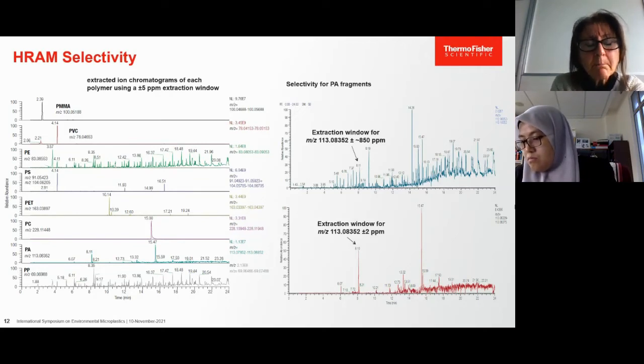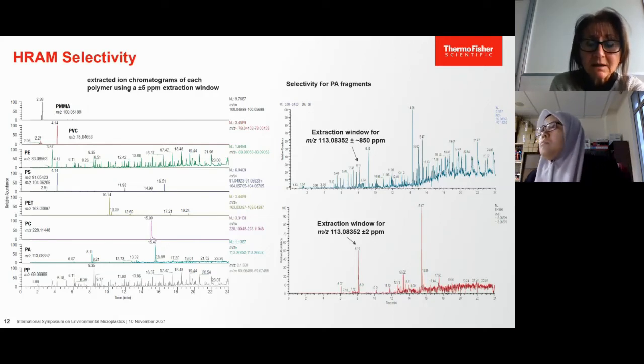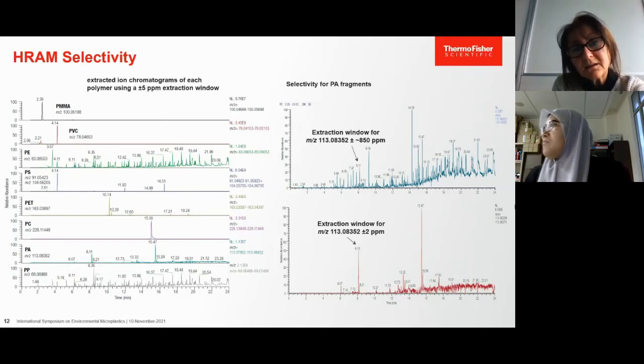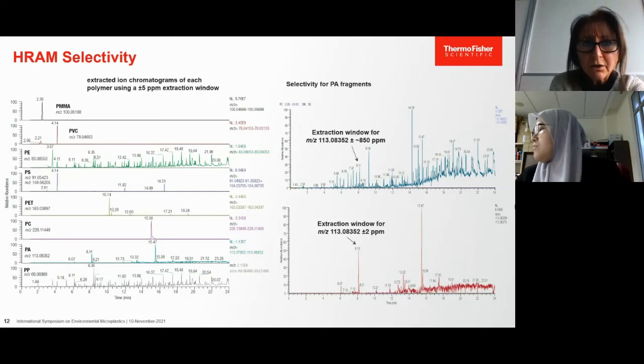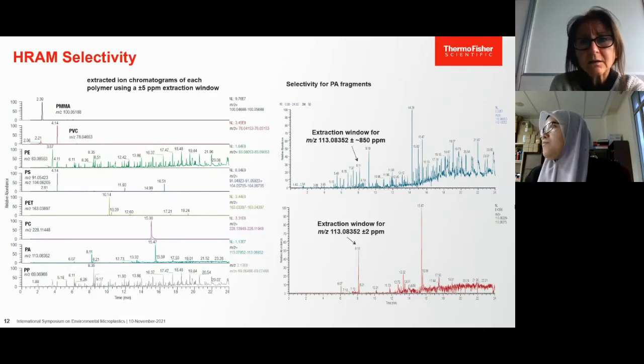In addition, the importance of high-resolution accurate mass detection in order to improve the selectivity is demonstrated on the right-hand side of this slide for the polyamide fragments, using a much wider extraction window in order to simulate a low-resolution mass spectrometer. As you can see, it is generating crowded extracted ion chromatograms. When using instead an extraction window of ±2 ppm and taking advantage of the measured accurate mass, the chromatographic peaks useful for the quantification are actually much more evident.